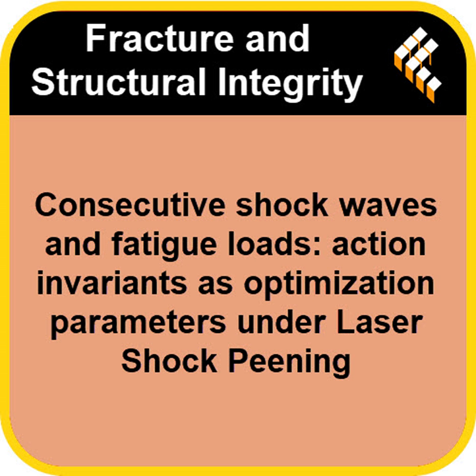But here's the twist, right? Our sources suggest the old ways of checking if this treatment worked. Yeah. They're not quite cutting it anymore. Yeah, that's the core problem. When you hit a material that hard and fast, the strain rates can be astronomical, like 10 to the 10th per second. Things happen differently. So measuring residual stress, the sort of leftover squeeze in the material, that doesn't tell the whole story. Not for these shock events, no. It's like trying to understand an explosion by just looking at the smoke afterwards. You miss the actual blast dynamics.